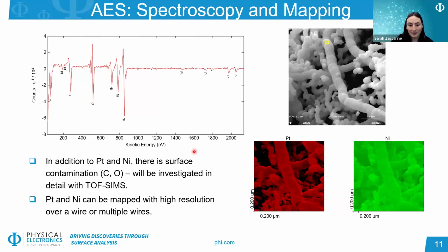We can then look at some spectroscopy to see what elements are present here. And we see our platinum coming from, again, the ALD coating, and nickel, which is the nickel nanowire template. As we would expect, we see a nice signal for both of these elements. We also notice that there's some carbon and oxygen present, which could be due to surface contamination. And we will be able to investigate some of those species in a little bit more detail with TOF-SIMS, but we can already see these clearly at the sample surface with this initial Auger spectrum as well.